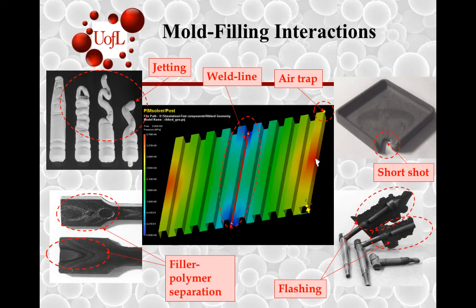Where are these considerations important? Let us take a typical injection molding scenario where a plate like this with all these channels is getting molded. It turns out that if you do not get the viscosity right, either by choosing an incorrect injection pressure or mold temperature or geometry, you can have premature freezing of the mold. That is called a short shot.